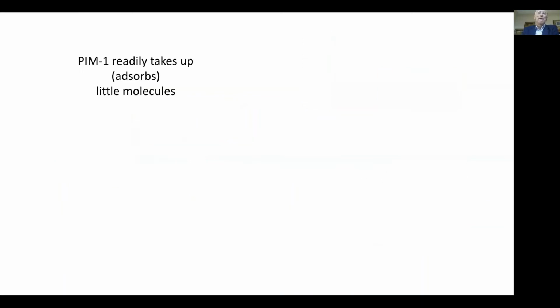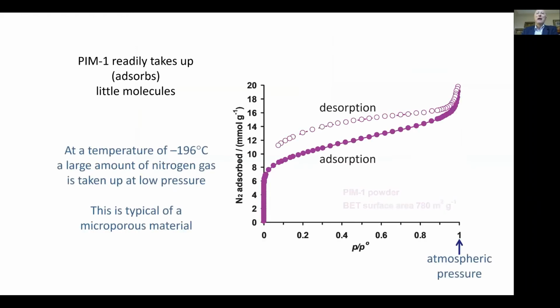And one of the features of this, the feature which arises from the way we try to design this polymer, if you like, is that it readily takes up, through a process we often call adsorption, little molecules. A sort of experiment which is often done for studying these materials is to study how nitrogen gas is taken up at low temperature, in fact the temperature of liquid nitrogen, minus 196 degrees centigrade or 77 Kelvin. And what we find is that at that temperature, that nitrogen is very, very readily taken up at very low pressure, much lower pressure than atmospheric pressure, by this polymer. In fact, it behaves as though it has an effective surface area of perhaps 800 square meters per gram of material.